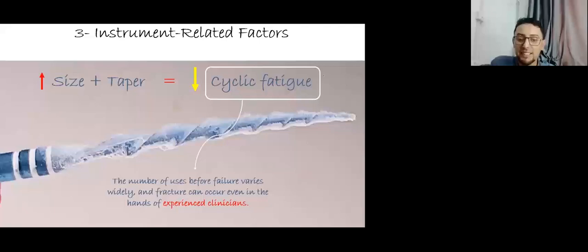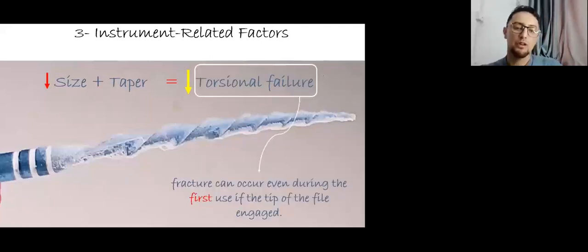So cyclic fatigue happens even in the hands of an experienced dentist or endodontist. While the small taper or torsional fracture happens due to its small diameter. It will happen even with a new instrument. Even if this instrument was used for the first time, if you didn't prepare the canal, you didn't do the glide path, smoothing the canal to ensure there is a smooth passage to the apex, with no narrowing or sharp binding of the canal that causes a fracture, the file will fracture even the first time it is used.